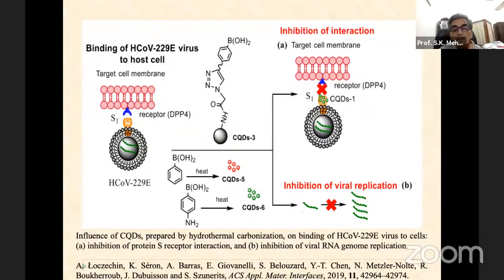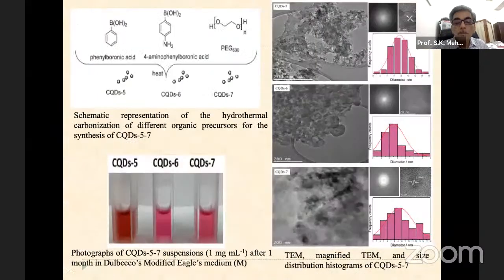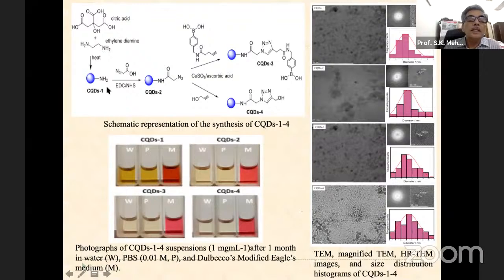So I thought this should be mentioned, that they prepared them by hydrothermal carbonization. Using hydrothermal carbonization, these quantum dots were prepared, and they bound with this virus to cells, and so many types of quantum dots they created. Quantum dots 1, quantum dots 2, 4, 3. By functionalizing, they used citric acid, ethylene diamine, and also functionalized with ascorbic acid, copper sulfate, and so on. So you can see different functionalization was done. A detailed study was done, and for the quantum dots from 1 to 4, which are shown here, they used a colorimetric method for the detection of the coronavirus.